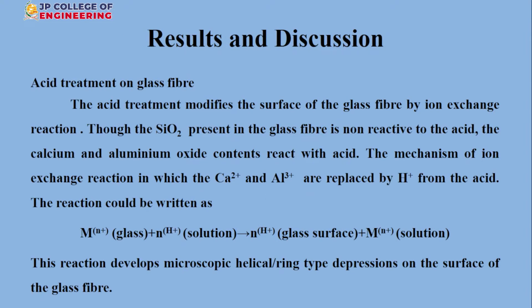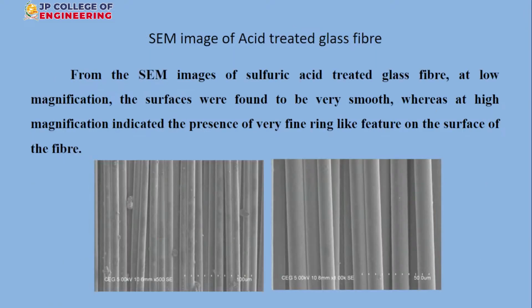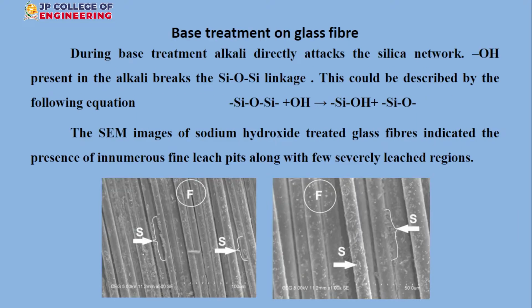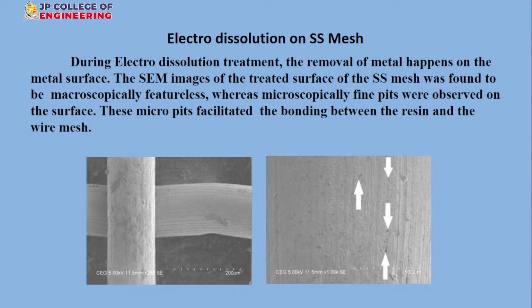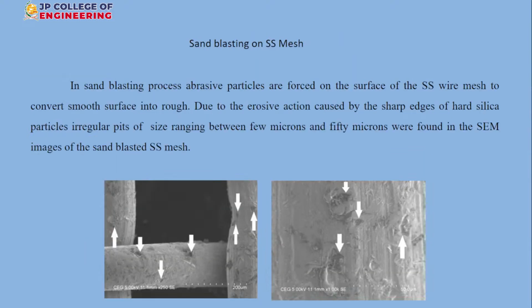So results, I will show that, since time is limited to 5 minutes. It's a picture to show that on treatment you get some micro pits. These micro pits facilitate the bonding, so that is the idea for giving surface treatment to the glass fiber. For the stainless steel, again, we went for electrodissolution, by which micro pits can also be produced. By sand blasting, using fine sand blasted over the stainless steel, we can get small pits. These pits will improve the adhesion. So once you do the surface treatment, then we made our composites.